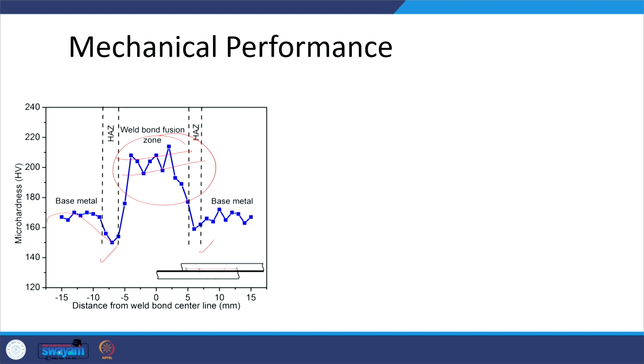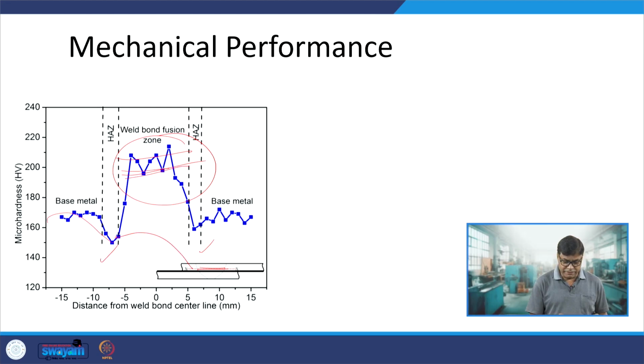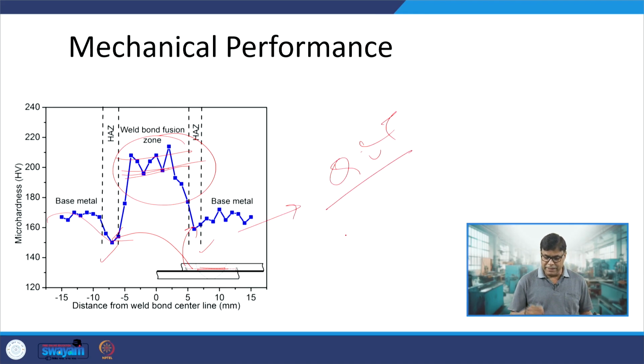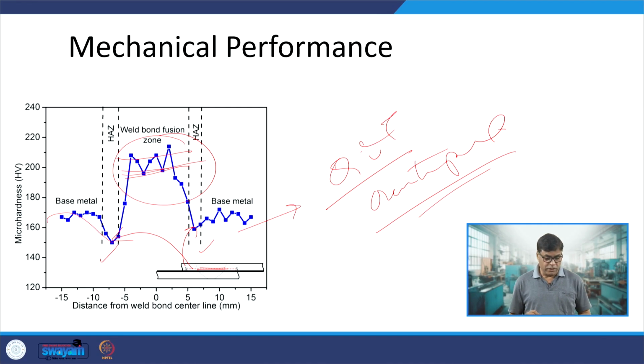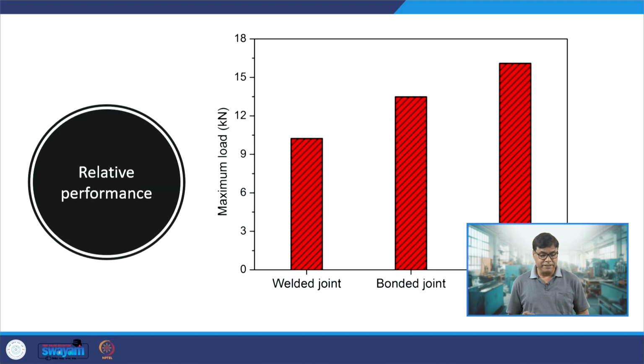Okay. So, this is the weld zone where our hardness is high, and in the heat affected zone hardness is less. We can say that if this steel was in Q and T condition, then over-tempering is attributed to this kind of softening, or the coarsening of the grain structure can also be attributed towards the softening of the heat affected zone.